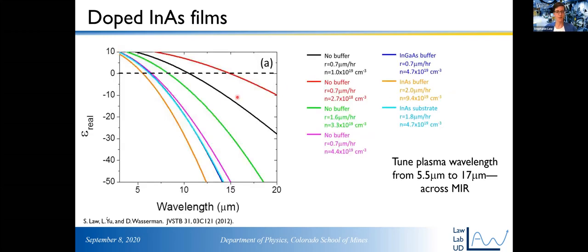So just to give you a really brief example, this really does work. What I'm showing you here is the real part of the material permittivity, right? Remember, if the permittivity is positive, it's a dielectric, and if the permittivity is negative, it's a metal. And remember, the point at which it crosses zero, that's the plasma wavelength. So you can see in all these materials, as we change the doping density, right? These are all different doping densities here. We're tuning the plasma wavelength from about 5.5 microns all the way to, I think, 17 in this case, and we can certainly go to longer wavelengths, right? So these are really very tunable materials. The growth is actually sort of tricky, but it's definitely doable.